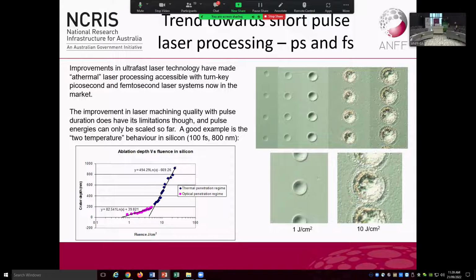And as you can see, we start off with these single pulse craters, which are beautifully smooth, not too much debris around. But as soon as we exceed a few joules per centimetre, which is a measure of the dosage on target, we then have a molten looking finish on the surface. We're clearly creating a molten surface in the silicon. So there's only so far you can push these processes before you run into these problems, which get you back into the same regime with nanosecond lasers.